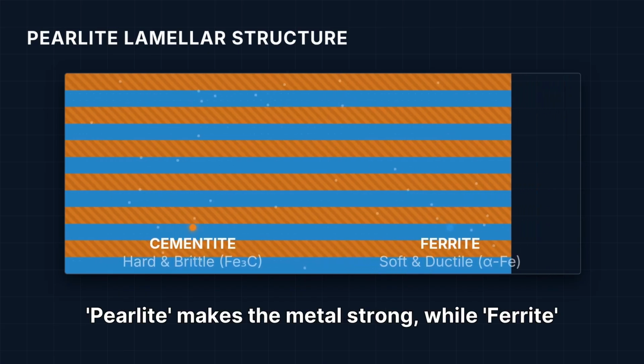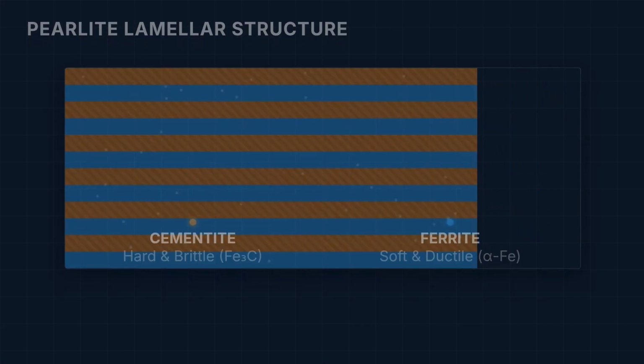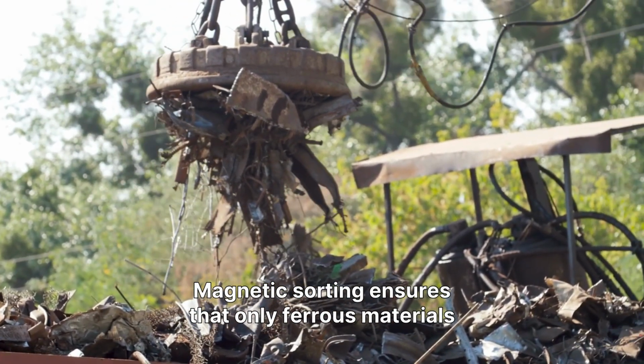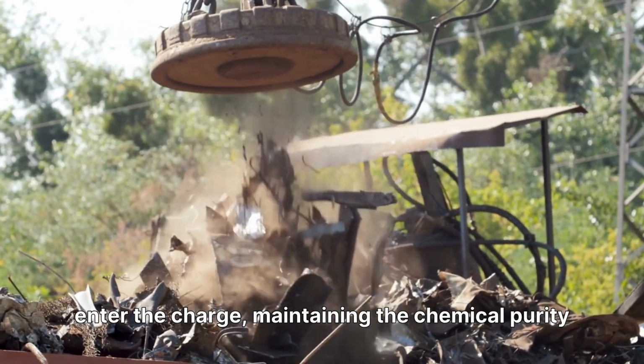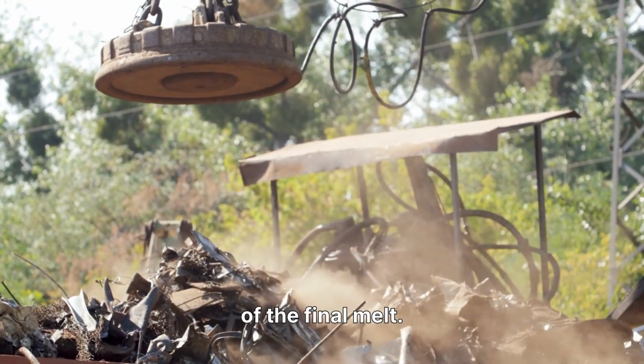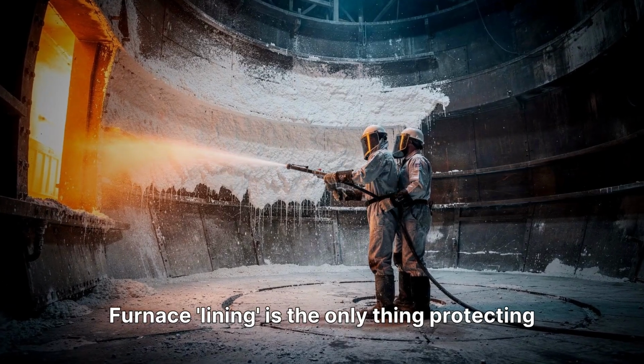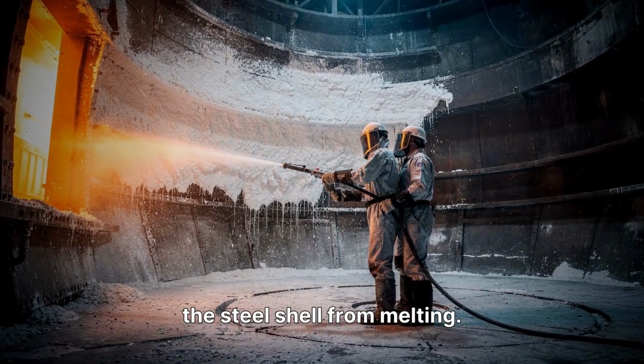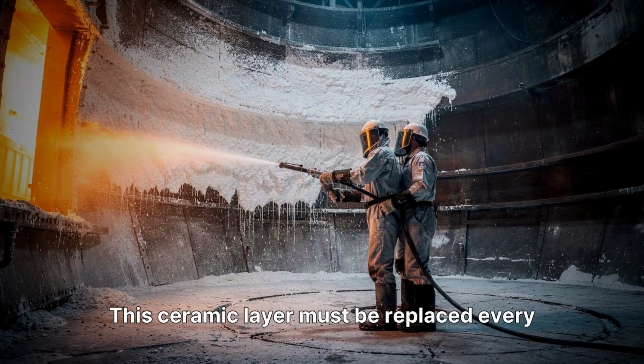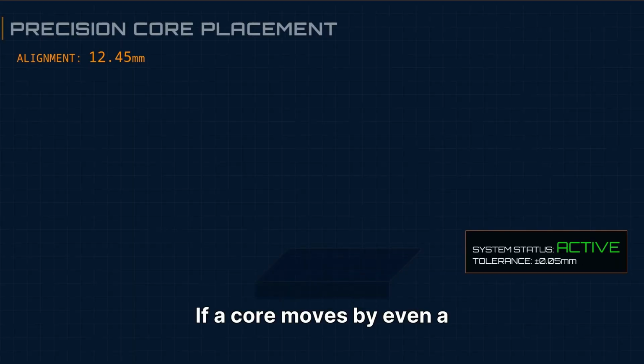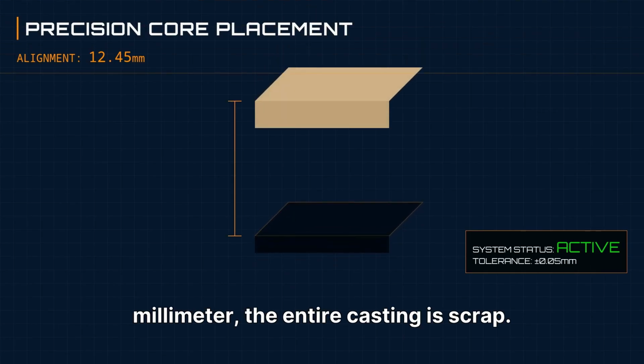Pearlite makes the metal strong, while ferrite makes it soft. Magnetic sorting ensures that only ferrous materials enter the charge, maintaining the chemical purity of the final melt. Furnace lining is the only thing protecting the steel shell from melting. This ceramic layer must be replaced every few weeks. If a core moves by even a millimeter, the entire casting is scrap.